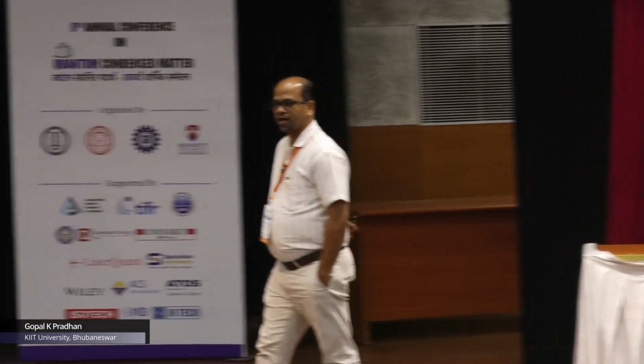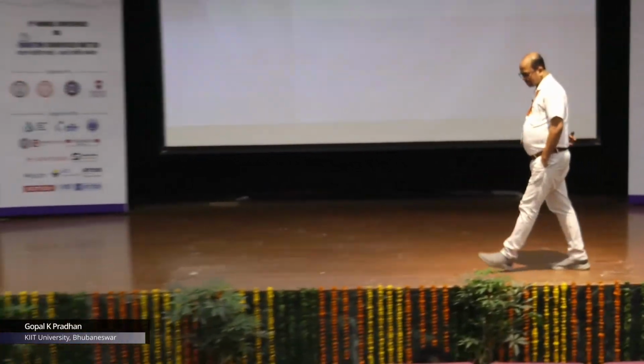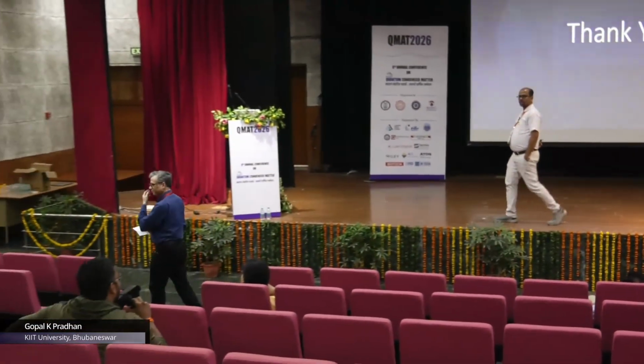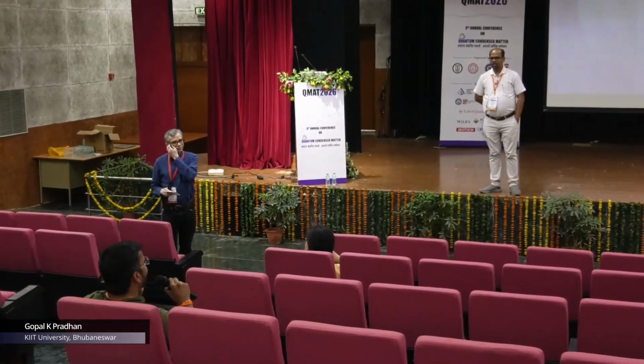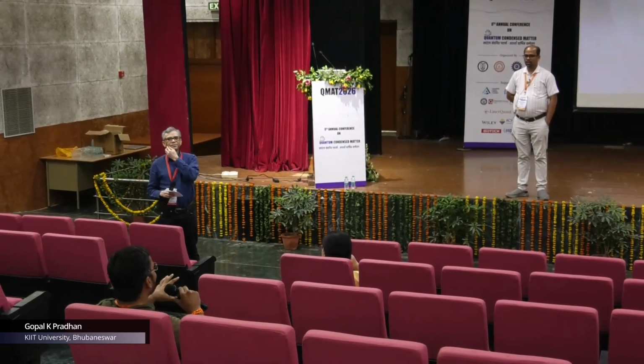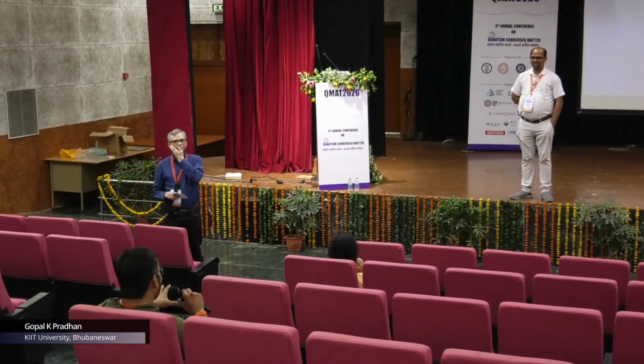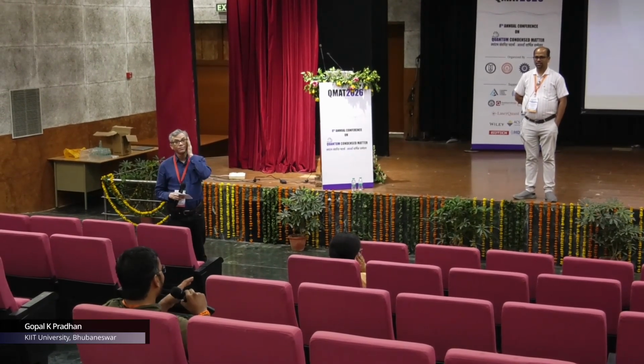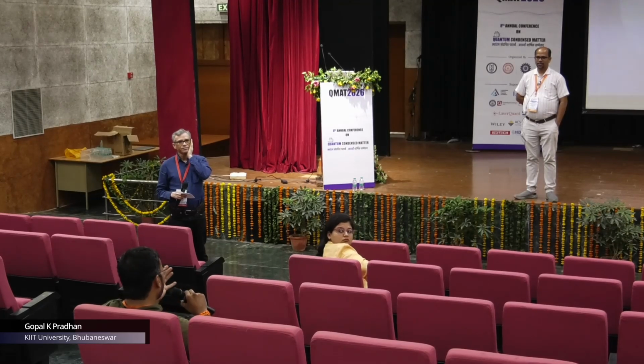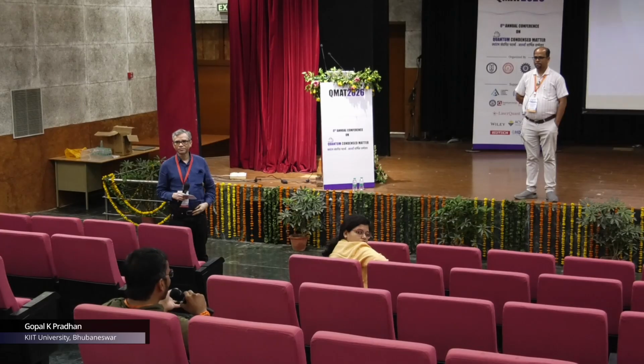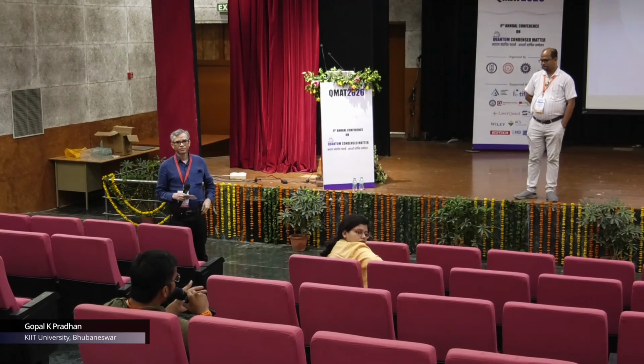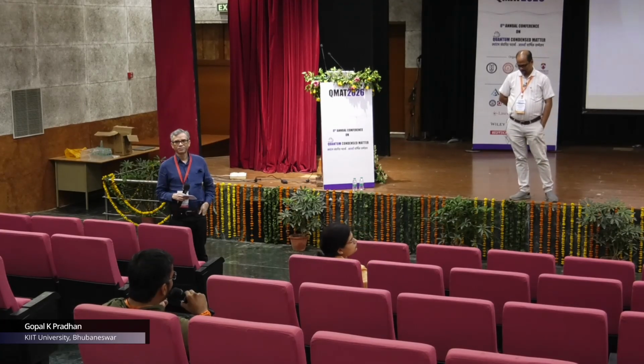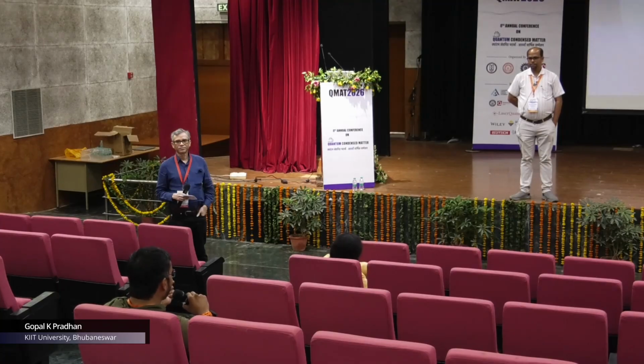Okay, give the mic. Hi, thanks Sunam, this was a nice talk. Although I'm a bit worried about the thermal conductivity part of it, more from a conceptual point of view. When you're looking at this photon interaction, you're basically probing the Raman active optical modes, while the acoustic modes, which are responsible for heat carrying, sit at the gamma point and do not necessarily need to thermalize with the optical phonons that you are probing in the case of 2D materials.